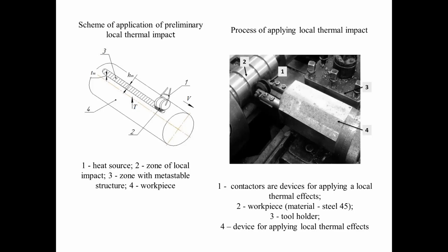The intersection of the localized heat influence with the surface layer of the part will result in a defect in its structure due to phase reverting reinforcement. This increases the density of dislocation and the tension in the crystal lattice, which contributes to the formation of a metastable structure in the local zone.